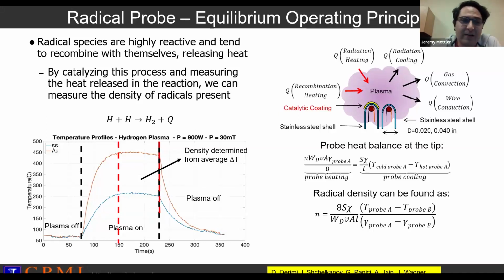That works great for things like hydrogen, which readily recombines on a wide variety of catalytic surfaces, but primarily gold is what's used for these probes. But this has not been applied to fluorine in the past, partially due to the intensely corrosive environment that's found inside of fluorine plasmas. They like to etch lots and lots of different metals, so it's a pretty punishing environment to put an intrusive probe in. And also the fact that, somewhat counterintuitively, while fluorine reacts very readily with metals, it actually has a relatively low recombination rate with itself. And so it has a low tendency to actually undergo this recombination reaction to form F2, and that can make it a little bit tricky to measure.